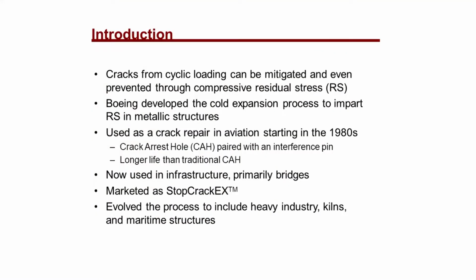More recently, in 1988, some of you may remember the Aloha Airlines incident where a 737 became a convertible in flight. That was also due to crack propagation between fastener holes. You know, holes are a stress riser, so they will cause cracks, and under cyclic loading, the cracks will continue to propagate. So Boeing developed a cold expansion process to mitigate this by imparting residual stress into metallic structures.